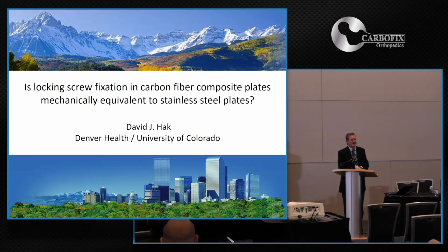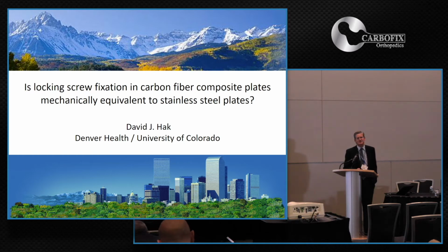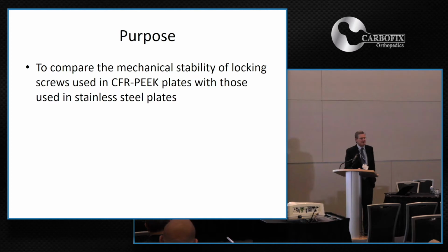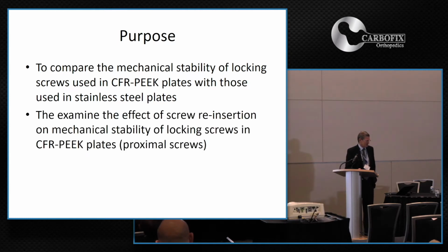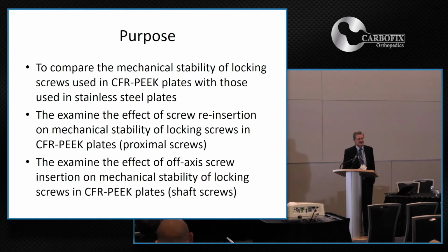So one of the questions that I had is the locking screw construct in these plates. How does it compare to, say, a stainless steel plate? And so we did a study to compare the mechanical stability in carbon fiber reinforced PEEK plates with those in stainless steel plates. We examined the impact of screw reinsertion in the PEEK plates. And we also examined the impact of off-axis screw insertion.